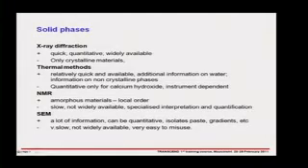It's got this huge advantage of being able to isolate the paste from the aggregate, also to look at microstructures, how they vary in time, for example, microstructural gradients, as you may get from a surface when you have a kind of degradation reaction. It's pretty slow. It's not all that widely available, and I think the biggest problem is you really need to have some experience, and it's often easy to misuse.